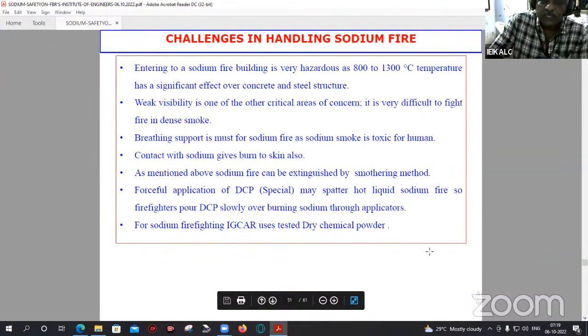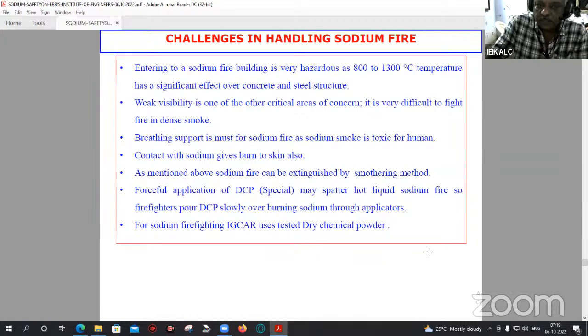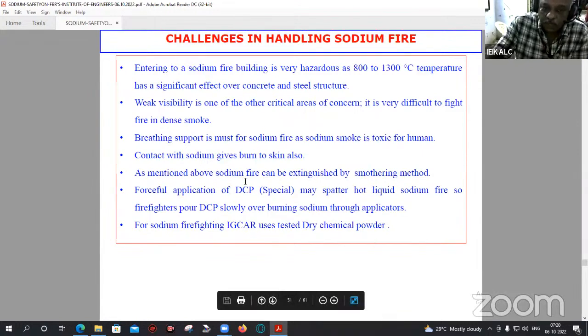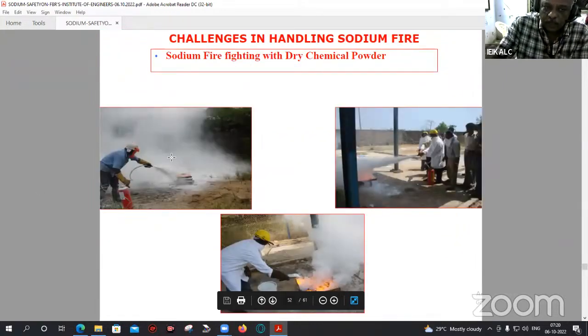A challenge in handling sodium fire is that entering a sodium fire building is very hazardous. There is a very large fire, and you have to take care of yourself. Personal protection is very important, provided you are protected with an SCBA device, and two persons need to go to attend to the sodium fire. Visibility is one important issue. Breathing support is required. And when sodium comes in contact with the body, it can give an alkali burn. We can use dry sodium bicarbonate based powder or ternary eutectic chloride to extinguish the sodium fire. These are some photographs which were taken during extinguishing of a sodium fire.